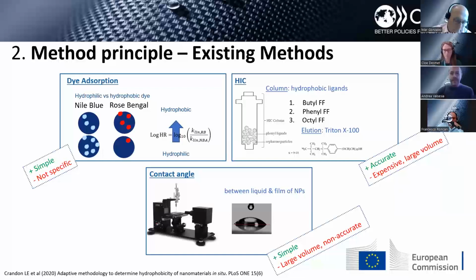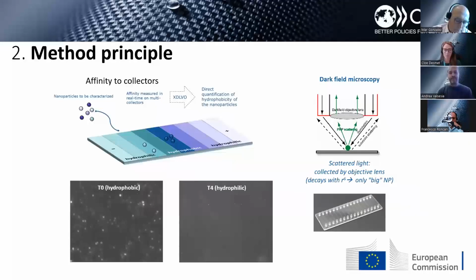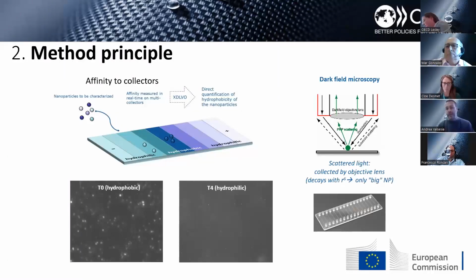This was one of the reasons why we decided to start this project: to develop a method based on the affinity of the nanomaterial to collectors, to surfaces. We have a surface which is hydrophobic, our hydrophobic collector, and then two surfaces which are hydrophilic, one negatively charged and one positively charged. By means of dark field microscopy, we are able to count in time the number of particles binding in real time to the different collector surfaces.